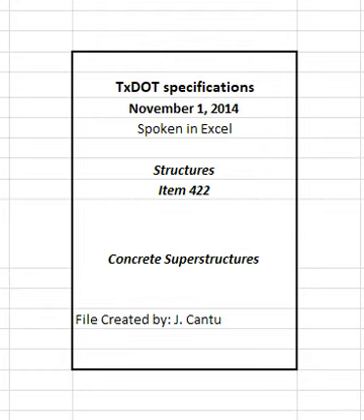3.5 Temperature recording equipment. Use strip chart temperature recording devices, recording maturity meters in accordance with TEX 426A, or other approved devices that are accurate within plus or minus 2 degrees F within the range of 32 degrees Fahrenheit to 212 degrees Fahrenheit. 3.6 Artificial heating equipment. Use artificial heating equipment as necessary for maintaining the concrete temperatures as specified in section 422.4.6.11, placing concrete in cold weather.